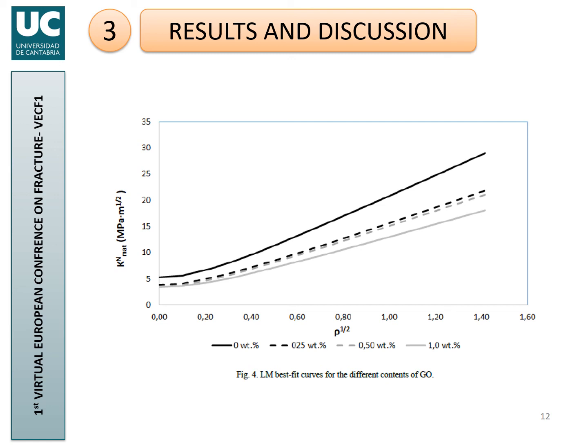The fracture toughness reduces. The notch effect, the increase in the fracture resistance with the notch radius, is quite similar in the different materials. Actually, you have in the paper the critical distance values for the materials, and they are quite similar for the four materials. But it is clear that there is no improvement at all when introducing nanoparticles on PA6, which is surprising if you look at the literature, and it has been quite disappointing for us, to be honest.